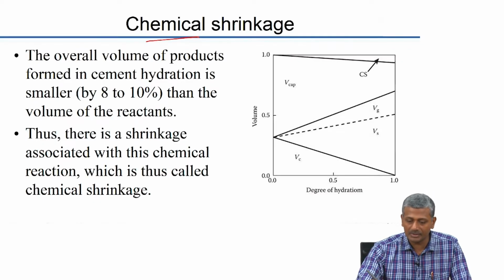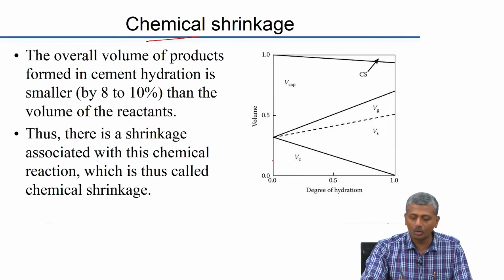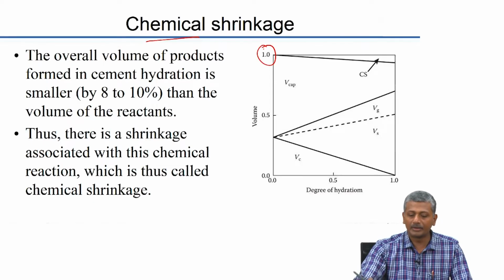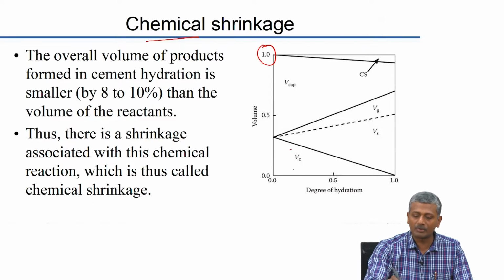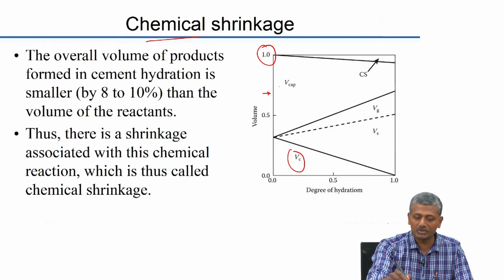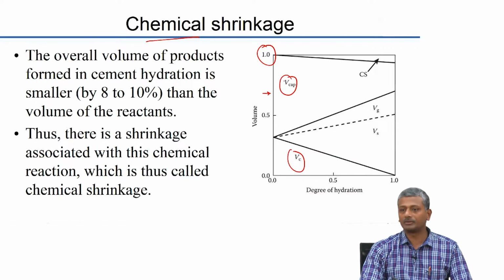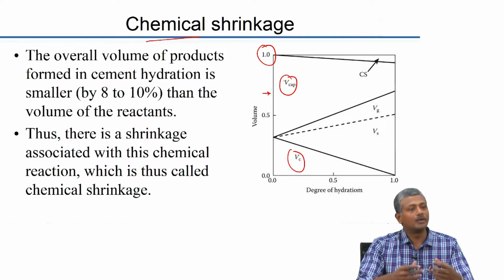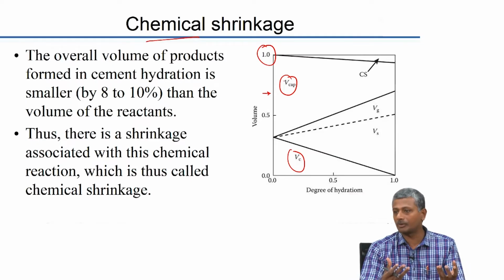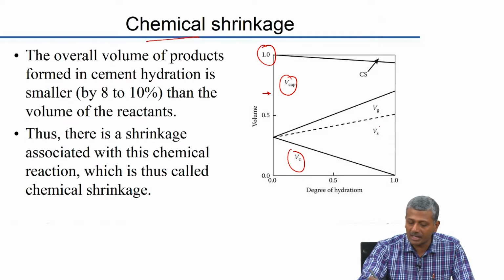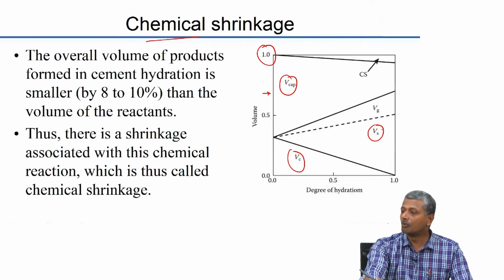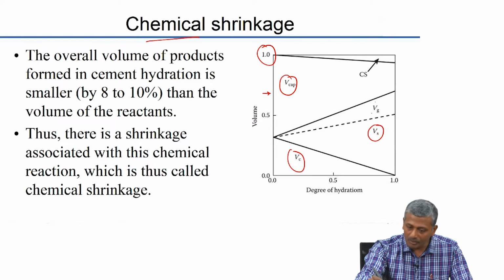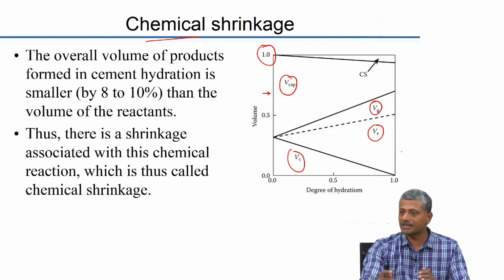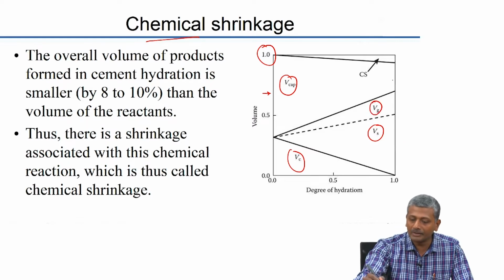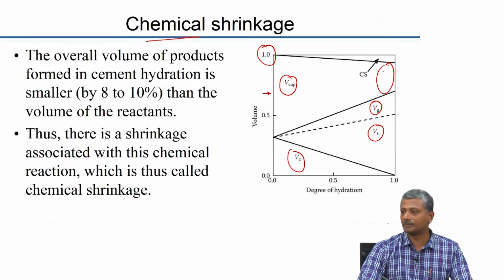So, what this is showing is, again, this is the initial volume of your reactants, that is 1, okay, and out of that this is the volume of the cement and volume of the water, which is marked as the volume of the capillary porosity, right. When cement and water are mixed together, all the water forms part of the capillary porosity. As more and more hydration happens, the volume of the solid hydrated cement paste keeps growing. Okay. The volume of the gel pores proportionately grows as the hydrated cement paste keeps forming, and the remaining fraction is your capillary porosity. Okay.